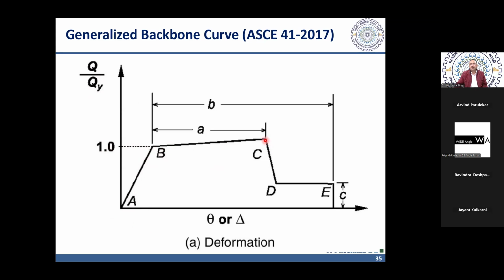B to C, and then at C, the concrete gets crushed. And when concrete gets crushed, concrete reaches its ultimate strain. In case of unconfined concrete, that is 0.0035, but actually the concrete is confined. So the strain at this level is of the order of 0.02 if it is properly confined. So it will depend upon the confinement. So if it is properly confined, then when the concrete gets crushed here, the strength is suddenly reduced. So you can see that there is a sudden drop from C to D. And then the member starts resisting the force through catenary action, and then finally steel ruptures here. So point E is the failure. Here the failure or collapse of the member takes place.